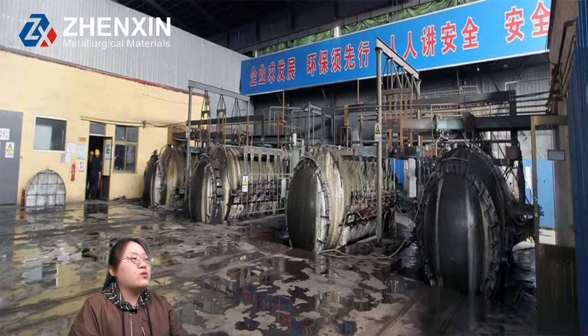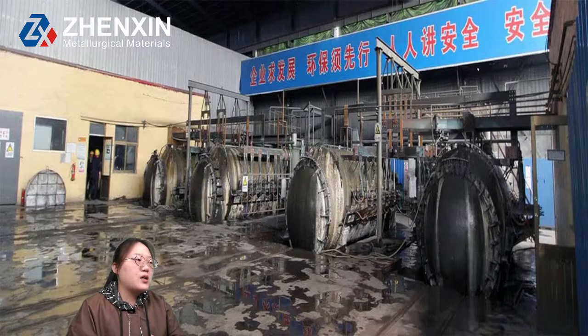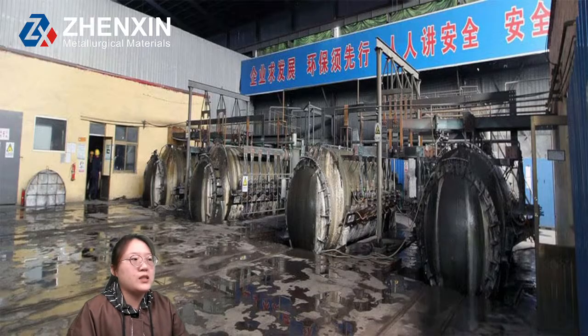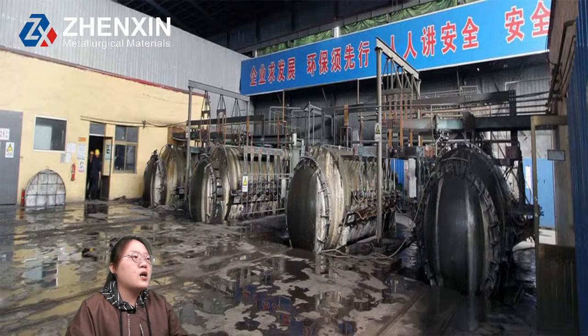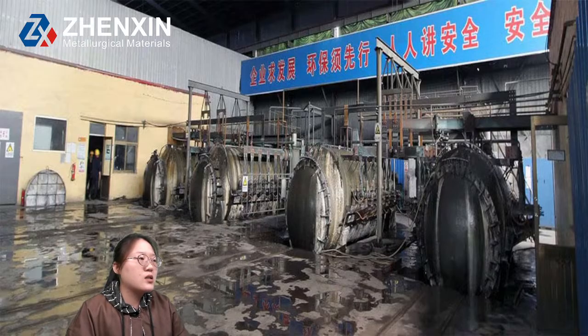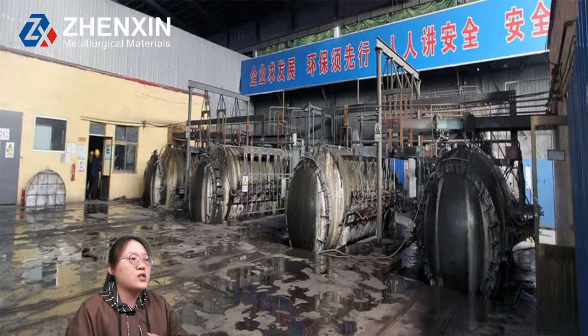The silicon barium inoculant strongly increases the graphitization curve, refines the graphite, promotes the A-type graphite in the gray iron casting, and improves the strength. For the ductile iron casting, it can make the graphite in the ductile iron fine and round, and improve the spheroidization grade. It has strong resistance to fading while preventing the associated spheroidization fading.